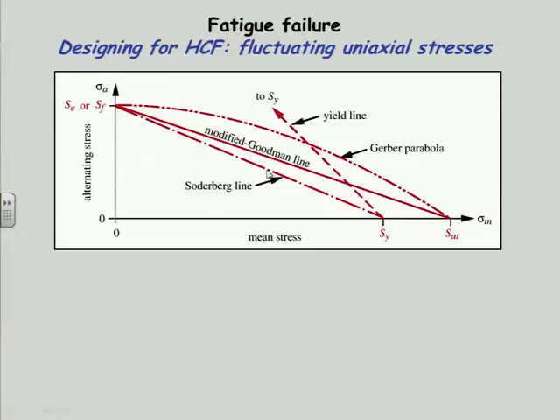Mr. Soderberg must have been extremely conservative, because note that the Goodman line simply connects the fatigue strength or the endurance strength, and whether it's endurance strength or fatigue strength is dictated by the type of material. We don't talk about an endurance strength for aluminum, because it never levels out. So we talk about its fatigue strength, and I use the subscript F for that. And if you're talking about a lifetime less than 1 million cycles, in other words, if you're only requiring the thing to last 100,000 cycles, then you could back up the curve, the SN diagram, and get a larger value for fatigue strength than the endurance strength, because they don't care about going to 1 million cycles. So that's the difference between the E and the F.